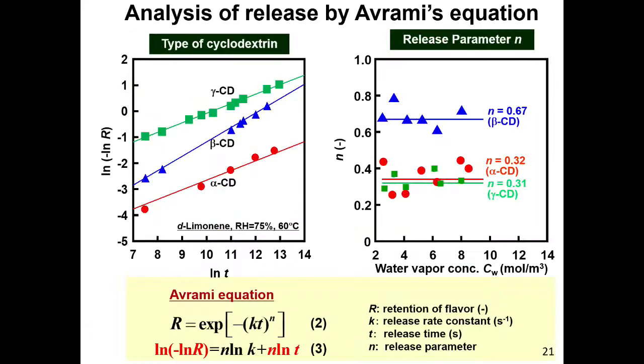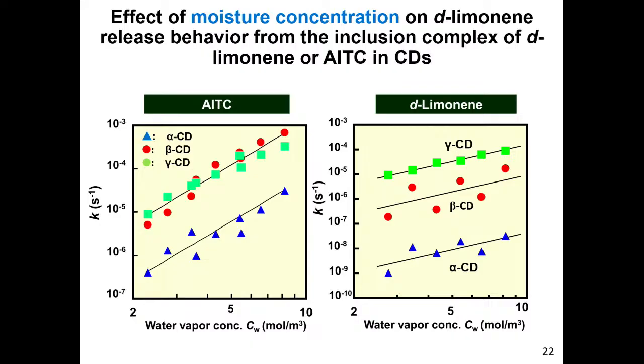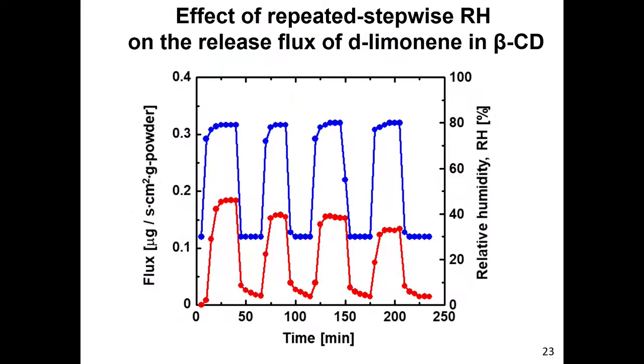So this release rate can correlate by using the Avrami equation. But I want to show the effect of repeated stepwise relative humidity on the release flux in beta cyclodextrin. The blue key shows the environmental relative humidity. The temperature here is about 50 degrees Celsius, a little higher. The red key, red solid line, shows the flux of the flavor compound from the powder.